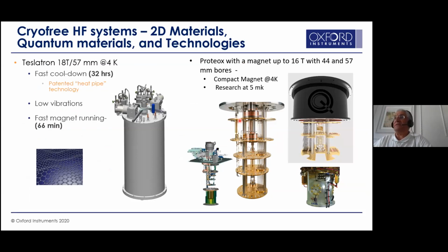So in addition to these systems, which are all wet systems, we have a family of cryo-free systems extending to 18 Tesla, completely cryo-free, with 57 millimeter bore and low vibration for graphene research at Manchester University. And in addition to that, we have provided systems which can take us to 16 Tesla in a very ultra low temperature environment, in a compact system running down to 5 milli-K. We have done 2 systems with 16 Tesla with 44 millimeter bore and 57 millimeter bore in a compact system.